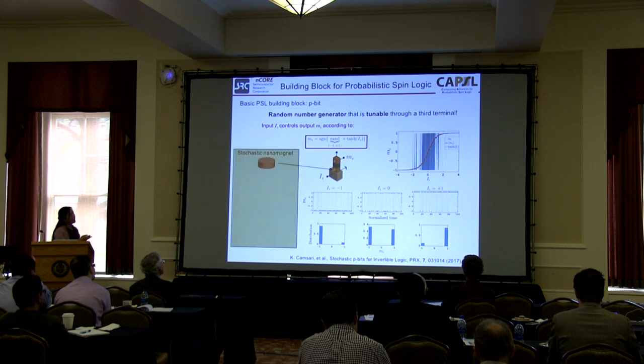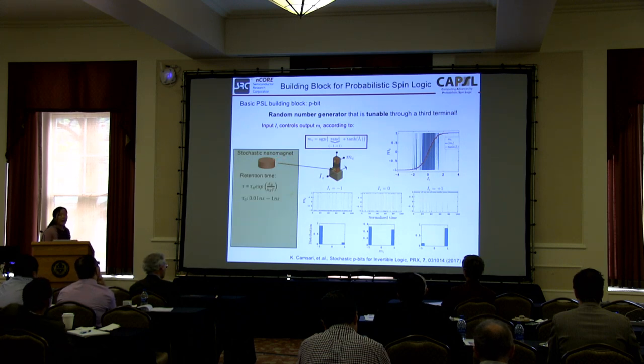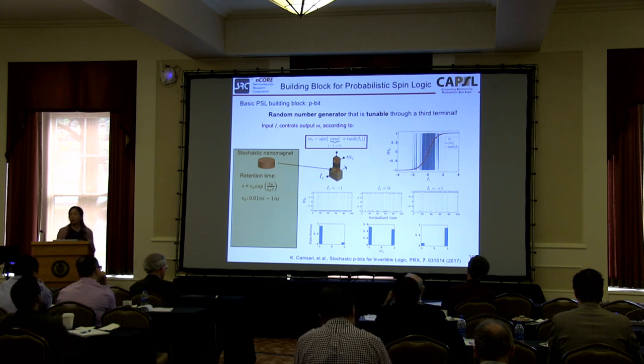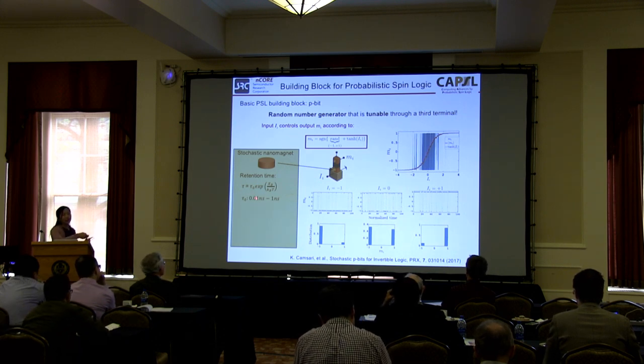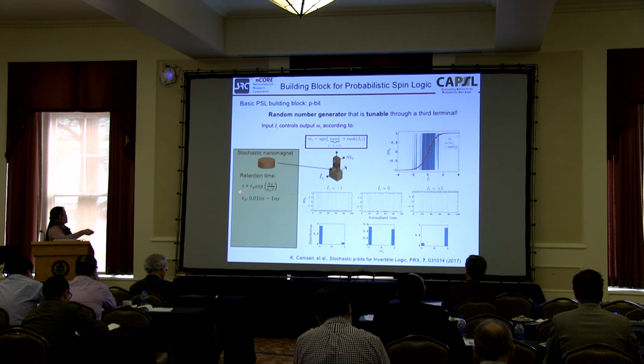And how do we actually get a magnet which is jumping, which we call a stochastic magnet, because it will jump between the two states? We know that the retention time for a magnet is described by this simple relation here. Tau zero is the material property. Depending on whether you are using cobalt, iron, boron, or permalloy, this tau zero will have different values. Typically, it's between 0.01 nanoseconds and 1 nanosecond. Then we see that the retention time is exponentially dependent on the energy barrier over kT. And as I mentioned, industry wants a really large energy barrier, 40 to 60 kT, so that it can have 10 years, 20 years of retention time.